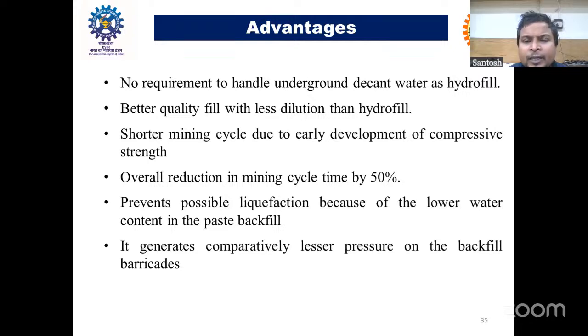For example, if we're doing hydraulic filling, the entire stope filling process, in some instances, may need, say for example, 30 days for filling a single stope. If you're using paste filling, the same stope can be filled within 10 to 15 days. So straightaway you are reducing the mining cycle by 50%. And also it prevents the possible liquefaction, and paste will create less pressure on the backfill barricades.